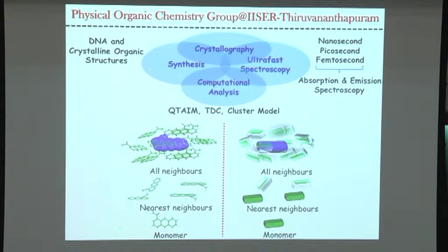So if you take organic chromophores and shine light on them, for the last 4 decades people have known a great deal about the excited state processes. But what is intriguing is when you have one more chromophore put adjacent to it: depending upon the orbital overlap between the 2 chromophores, you get totally different behavior. As I mentioned earlier, it can at times be singlet fission undergoing triplet generation, or triplet annihilation giving singlet. It can be enhanced fluorescence, and at times it can be charge transport that you derive out of it.